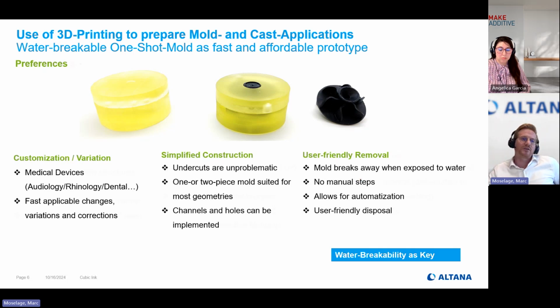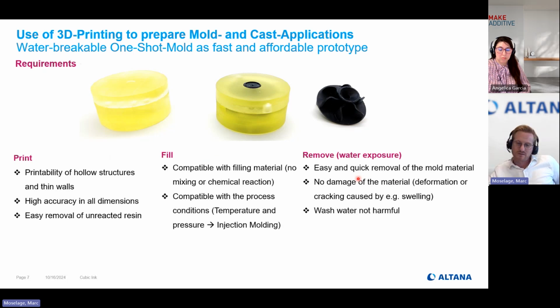Now, coming from preferences to requirements, what properties does this mold material have to contain in order to fulfill all these criteria in the process? Basically, the requirements can be characterized into three categories: the printing, the filling, and the removal. For printing, you need to be accurate. You need to print hollow structures and thin walls, so you need high accuracy in all dimensions, X, Y, Z. And additionally, an easy removal of the unreacted resin. This is something you always have when you do VAT polymerization, DLP, SLA printing. You have your VAT with the resin, and you need to remove the resin after printing.